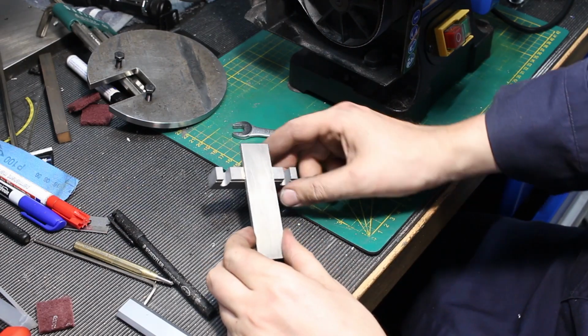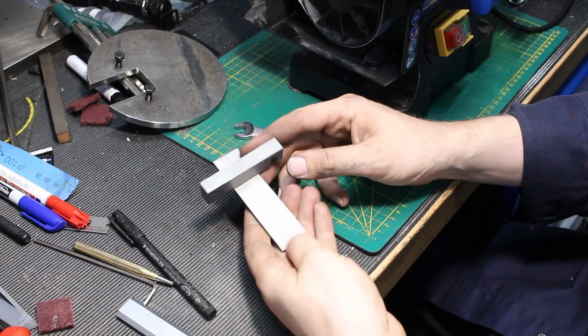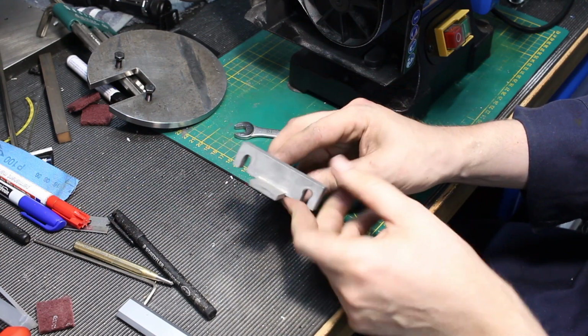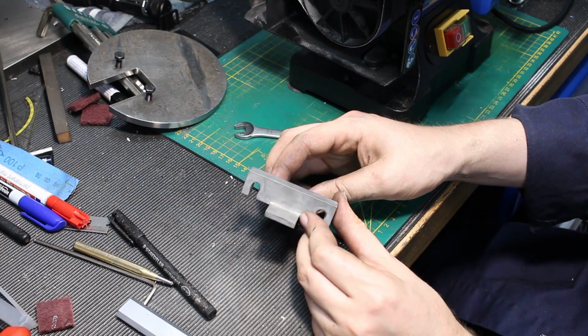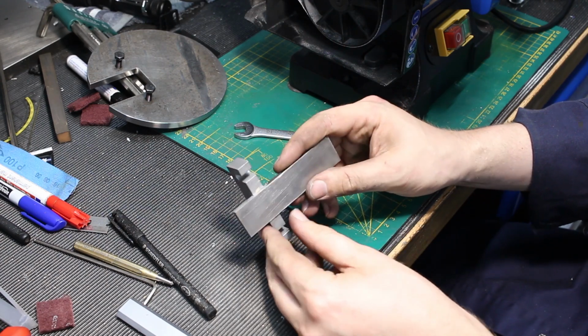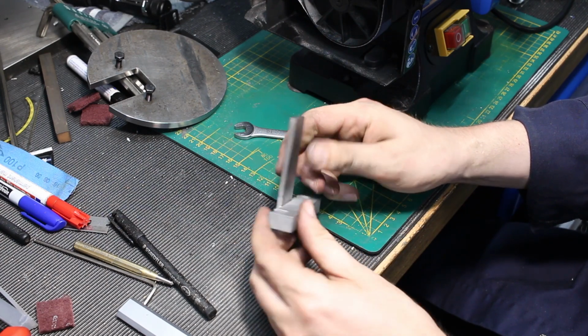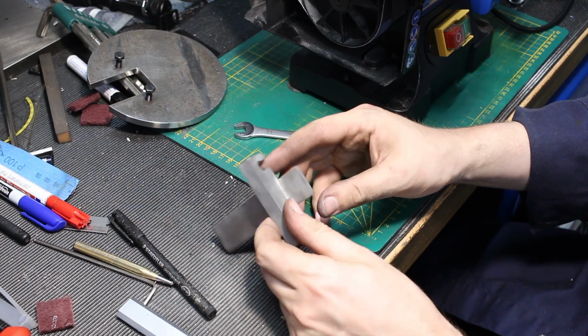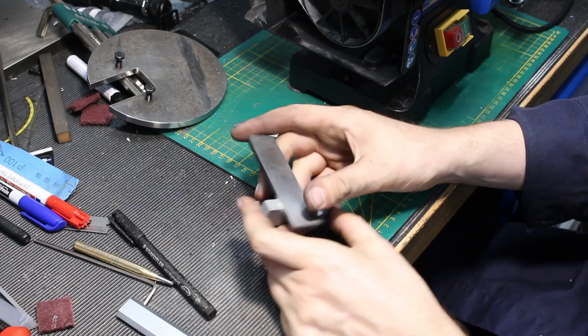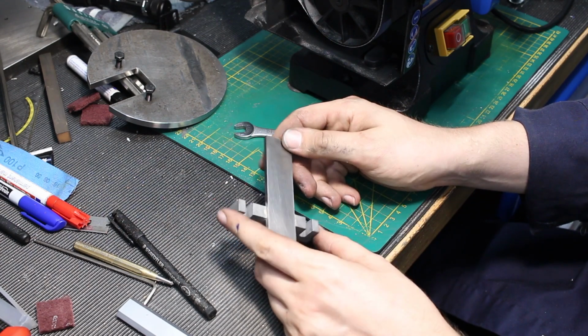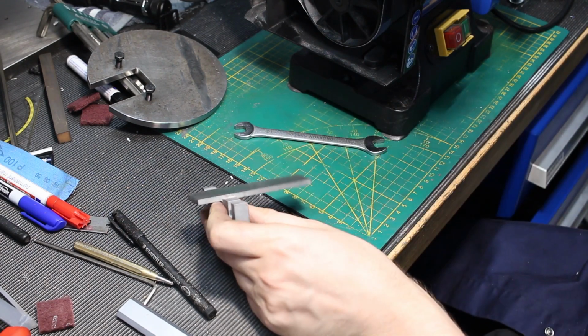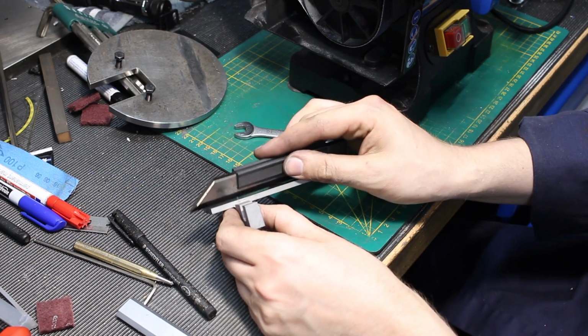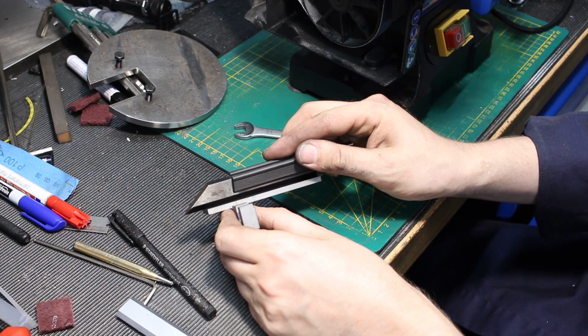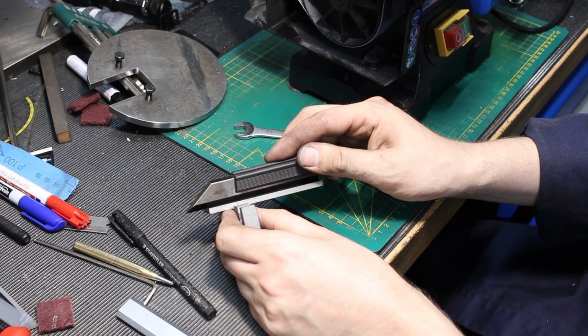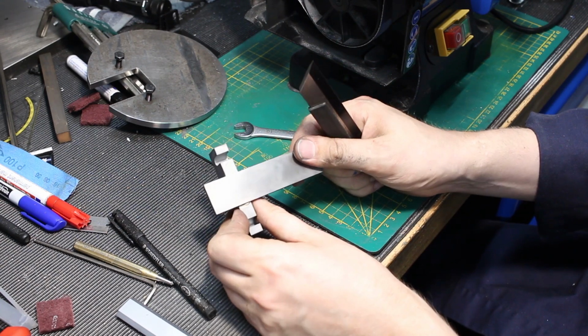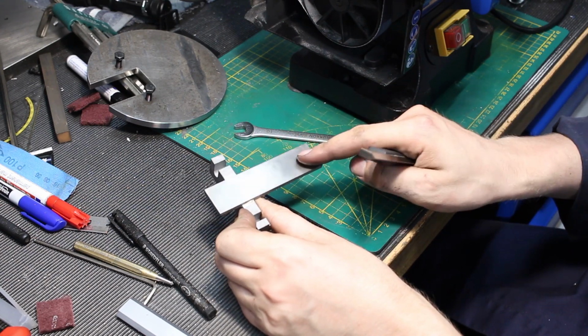Okay, I bead blasted the parts and they come out nice. The solder joint is relatively decent. It's okay. I got some silver here and here. It wicked through to the other side. Should be a sound joint. I don't worry. The nice thing about silver soldering compared to welding is that the distortion you get from silver soldering is very, very small. I'm probably not going to regrind this flat surface here.